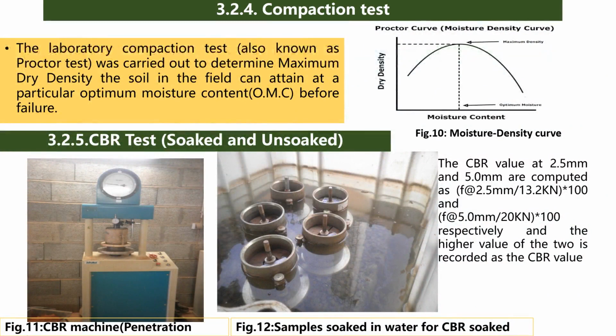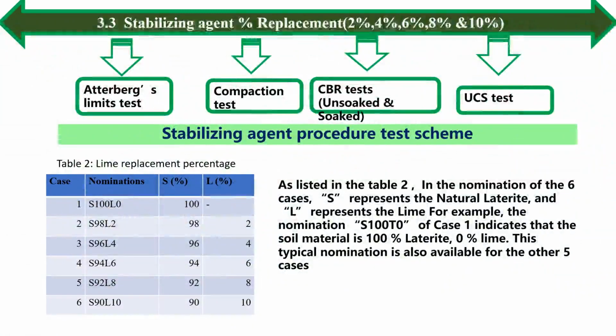The stabilizing agent entails the replacement of the soil sample with lime of 2%, 4, 6, 8, and 10%. And at the end of this, each of these four tests indicated are carried out to know the effects of the lime on the strength of the soil using each of these four parameters.